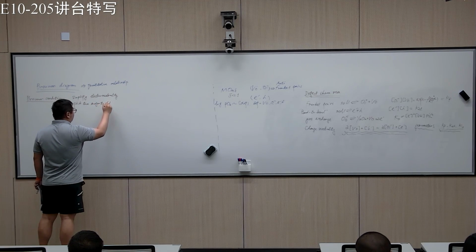Essentially, the way to do that is to pick two majority defects. These two have to be one negative and one positive. Why? If you pick two majority defects that are both positive, you can never satisfy charge neutrality, right?